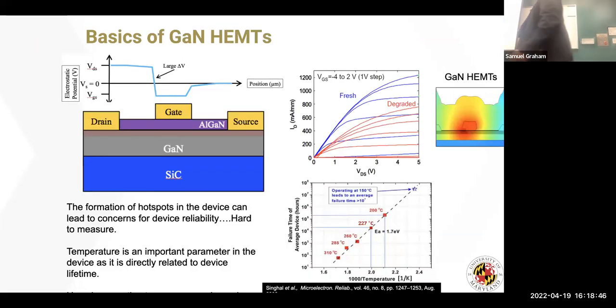So the key thing that I want you to remember is that in order to get that two-dimensional electron gas, I have to put two materials together. This interface, or the interfaces that you see here in this structure, can also block or impede heat transfer. So I have to worry about these interfaces, but they're necessary for the creation of these devices. Gallium nitride and silicon carbide, this interface with the two-dimensional electron gas.